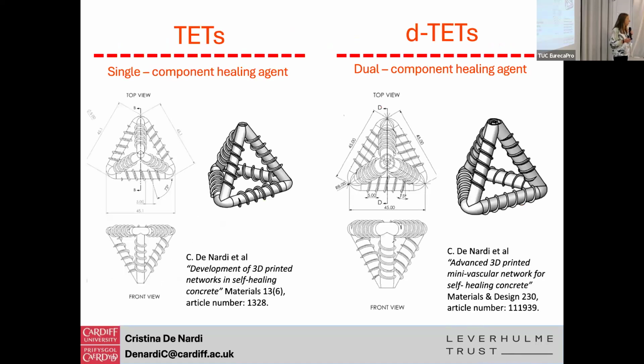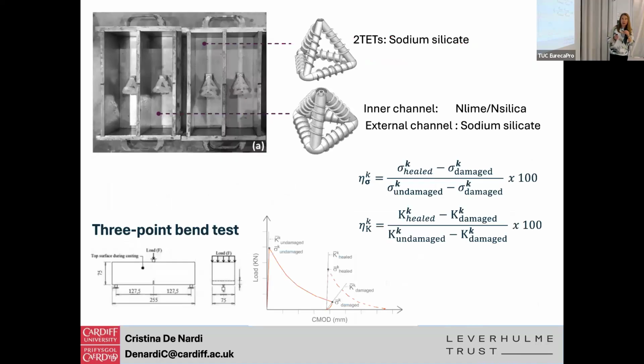So they can store a single component healing agents, basically silicates, or they can also store a dual component healing agent, as more of the most common adhesives are made of two components. They are made by two coaxial channels. So when you have a rupture, the crack also occurs in the matrix. The stress can be transferred to the units. You have the breakage of the units, and only at that time the two components are together and can react in the concrete matrix. We test them in a lab scale at the moment.